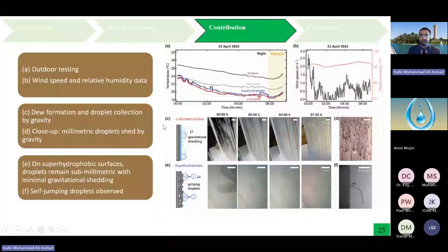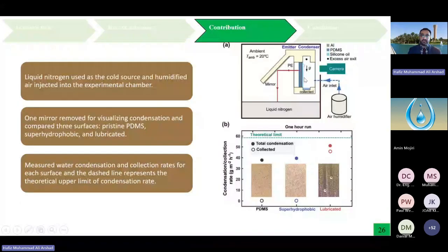So here you see that the testing was also done indoors, where we produced the sky effect by using liquid nitrogen. Here we were interested to see what would be the impact of different coatings. For example, if we only have PDMS, or a super hydrophobic surface, or finally a lubricated surface. PDMS and super hydrophobic surfaces had condensation observed, but the collection rate was very small.